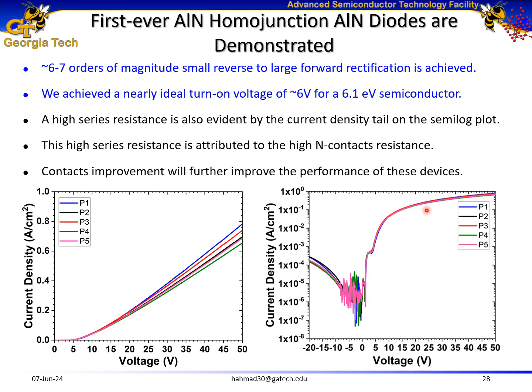However, we see a high series resistance evident from the long tail of the semilog plot, which is attributed to the high N-type contact resistance, and with improvement in the contacts, we can achieve even higher performance for these devices.